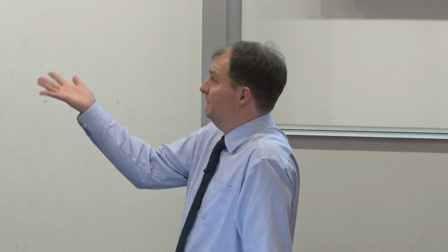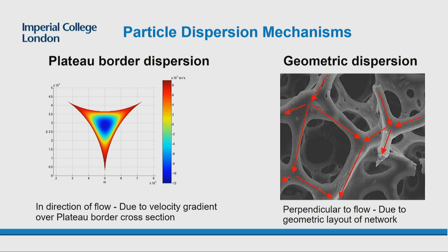There's what you might refer to as a plateau border dispersion. You've got these plateau borders which are being dragged upwards by the bubbles. They have liquid draining downwards inside them. So the liquid near the edge of the plateau borders is going upwards relative to the liquid in the middle, which means that a particle near the middle of the plateau border goes downwards relative to a particle near the edge. And this, of course, causes particles to spread out. The other one is a geometric dispersion. These plateau borders form a zigzagging network of channels. So every time they get to a junction, a particle basically has to make a decision as to which way it goes, which causes it to spread out at the same time.